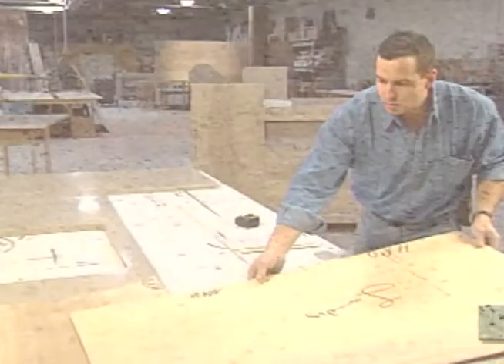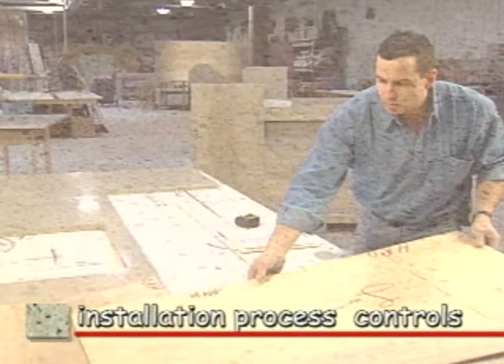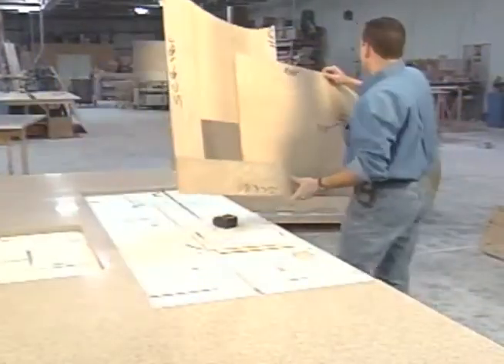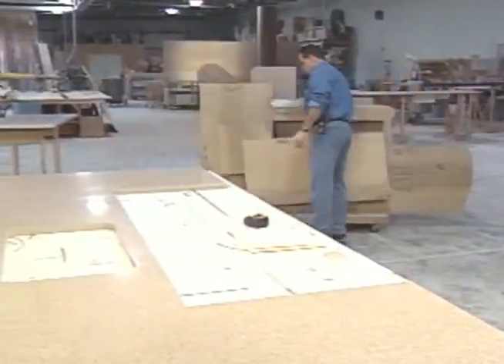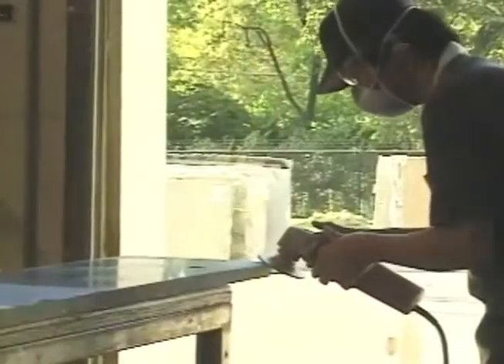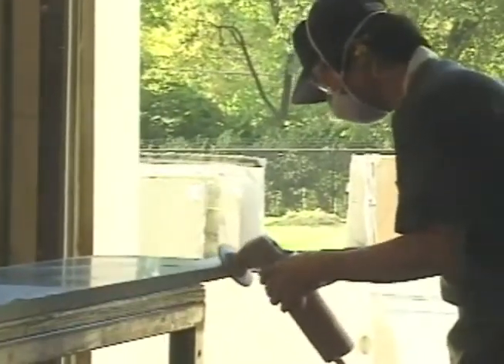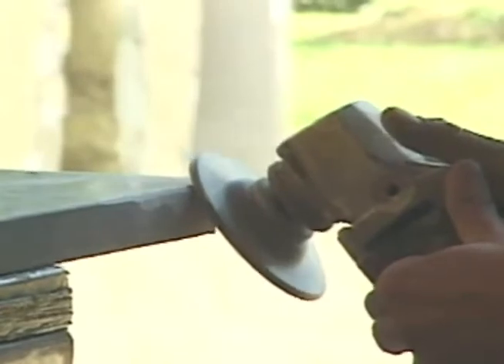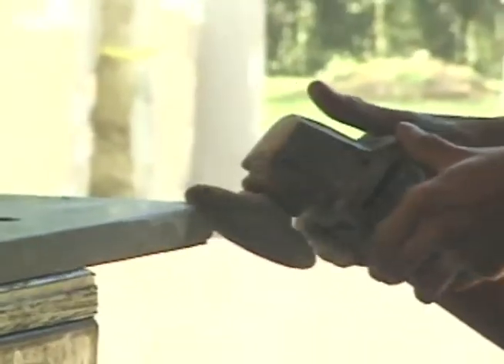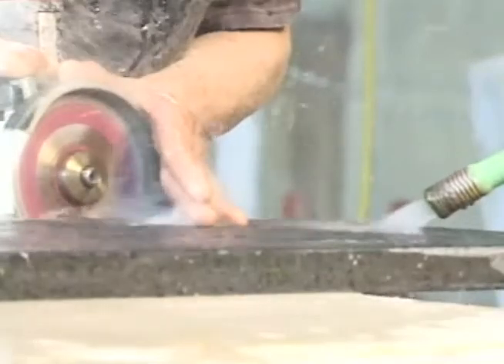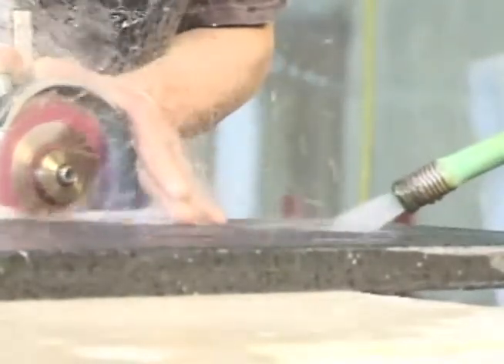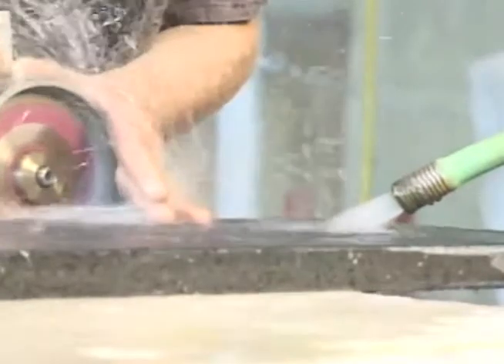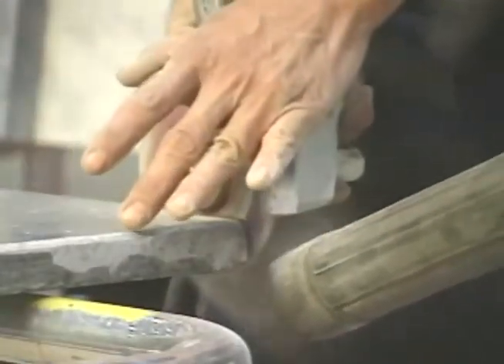The most effective way to minimize respirable silica dust generation in the field is not to produce any dust. This is accomplished by minimizing or eliminating field fabrication through the creation of accurate templates. When field fabrication cannot be avoided, any grinding, cutting, or shaping should be performed wet and/or performed outside. If fabrication outside is not possible, the HVAC ventilation system in the vicinity should be sealed off, and the fabrication should be performed wet or with local dust collection, such as a handheld vacuum fitted with a HEPA filter.